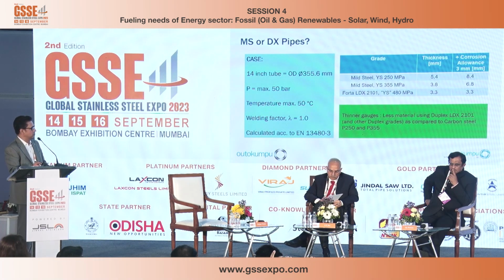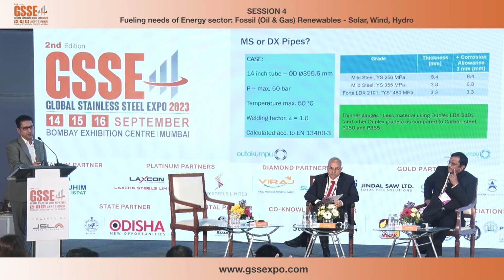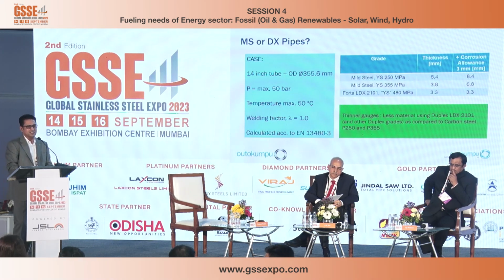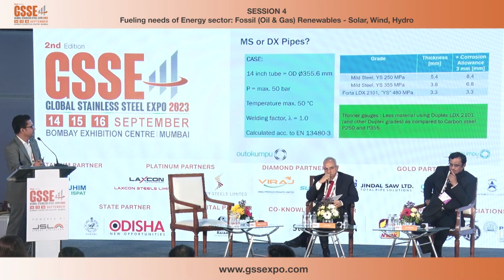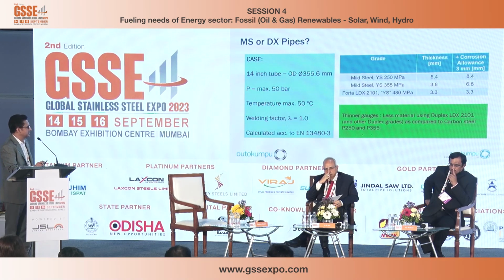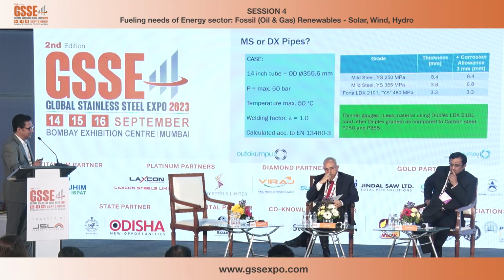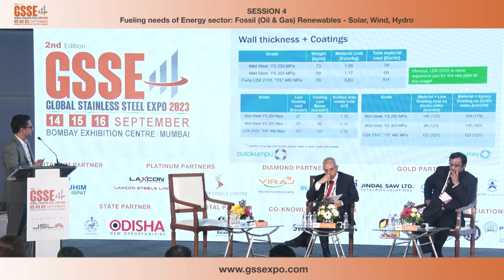In carbon steel or alloy steel, you have to add 3 mm. So the final usable thickness is 8.4, 6.8, whereas in super duplex or any duplex grade, you don't have to add the corrosion margin. Because if you see the values of corrosion on the ISO charts or any corrosion figures, it is less than 0.1 mm per year. So you can use the thinner gauge in LDX 2101 or any other grade in comparison to 250 or 355.